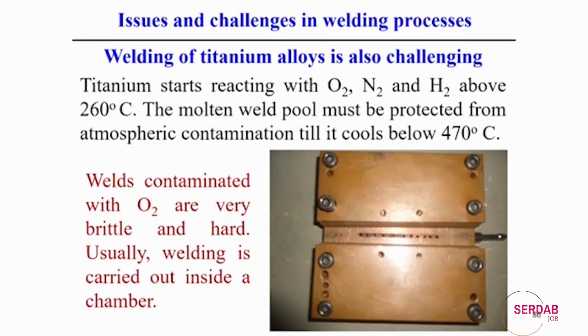The extra shielding gas actually comes from this small hole, if you look into this fixture, so that it actually protects the titanium alloy during the welding process. So, this is one of the easiest solutions for welding titanium alloy. This type of extra arrangement of shielding gas may not be required when you do plasma arc welding or tungsten inert gas welding. So, that is how to protect against this oxidation problem to some extent in the case of welding titanium.